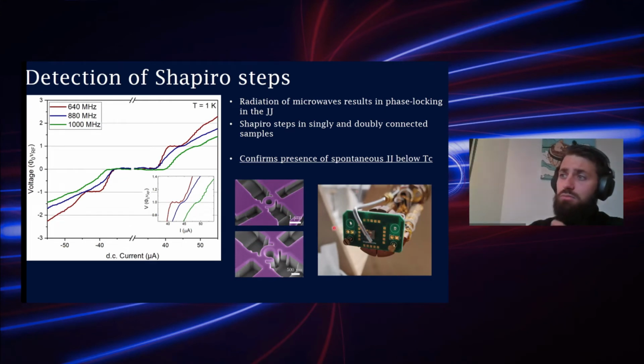And for both doubly connected and singly connected samples, so both one arm of the ring or two arms of the ring, we found these plateaus in the IV characteristic while radiating the sample, which are a clear signature of Josephson behavior. So this means that we are definitely dealing with spontaneous Josephson junctions that are appearing in these homogeneous rings.